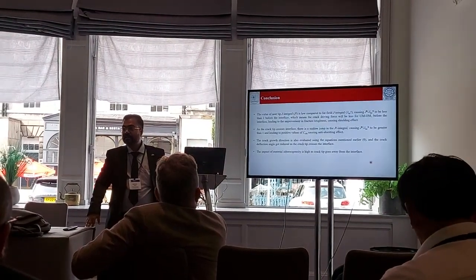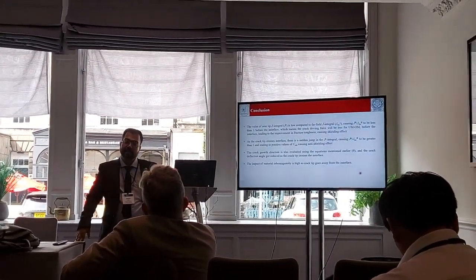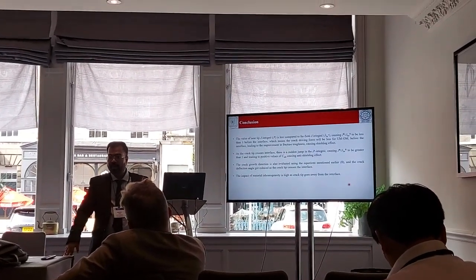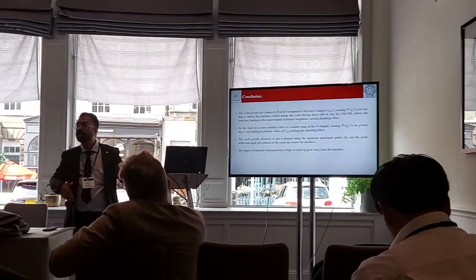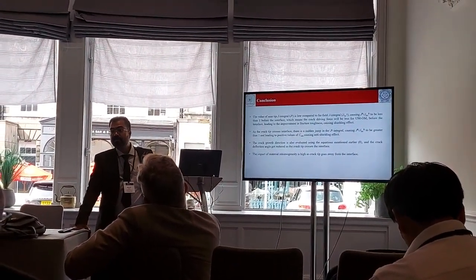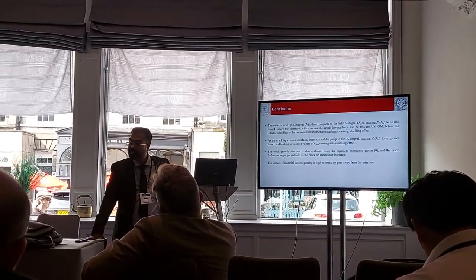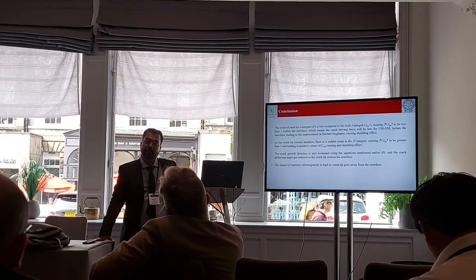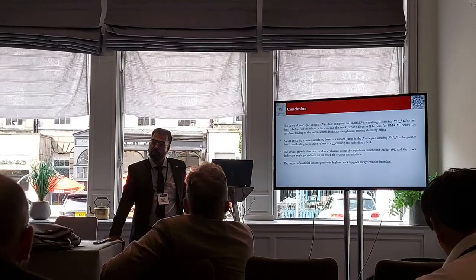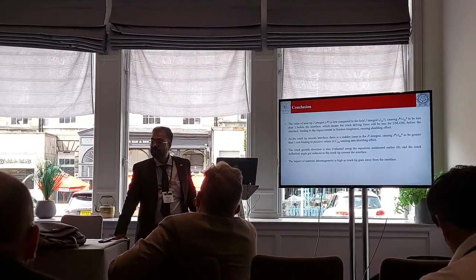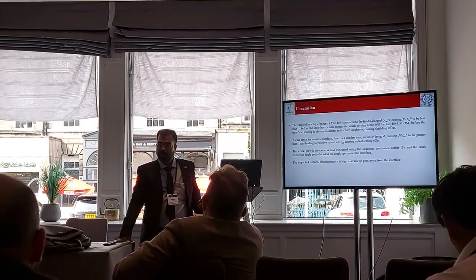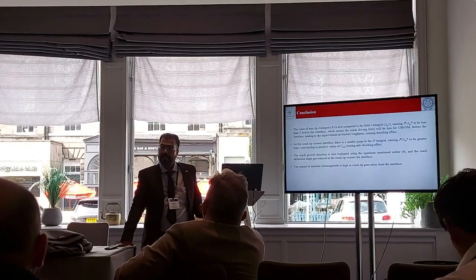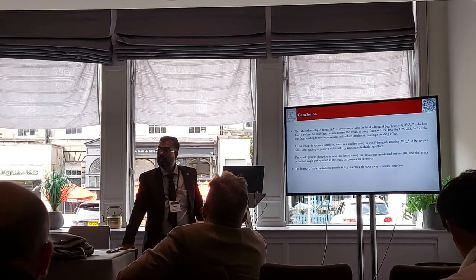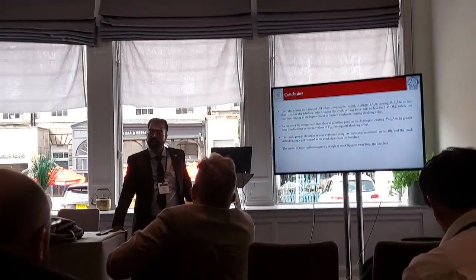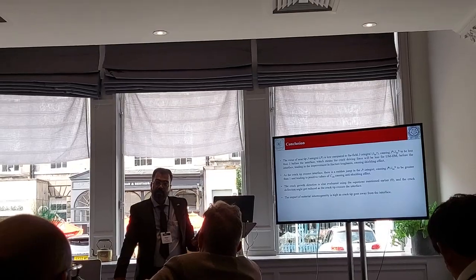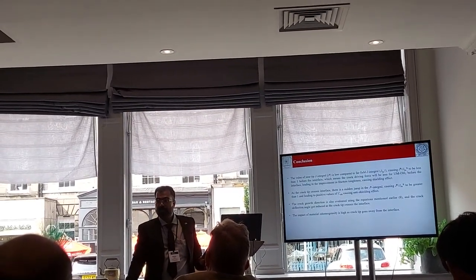So the conclusion is that the J integral, theoretically, which is given by James Rice, has some problems when you have unloading and when you have non-proportional loading. So that means when you have three differently deforming materials. And the concept of configurational forces, the advantage is that it does not assume anything about the constitutive relation of the material. So it can be applied in any kind of deforming material, any kind of loading condition, so three-point bending, tension, compression, or creep, or fatigue, or plasticity, anything, a combination of these, and it is away from any of the anomalies which are there in the theory. So theoretically, this concept is very sound. You cannot implement it experimentally, but numerically, it is very sound and it gives you a correct prediction.